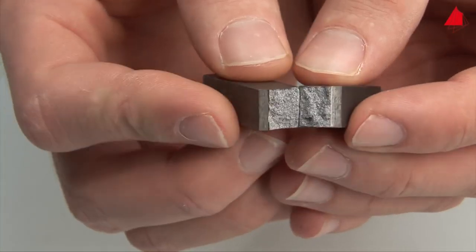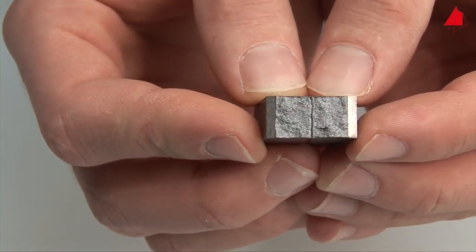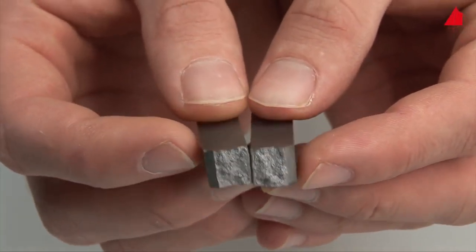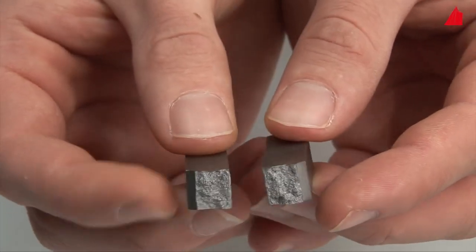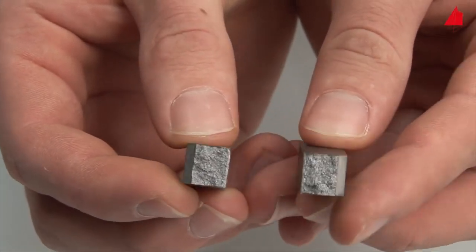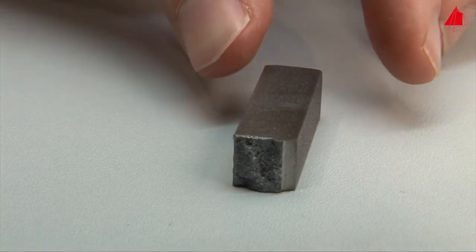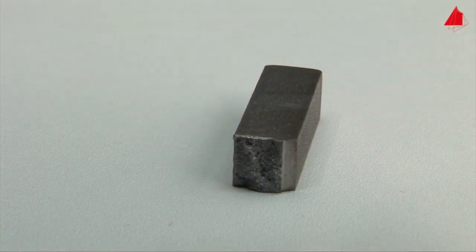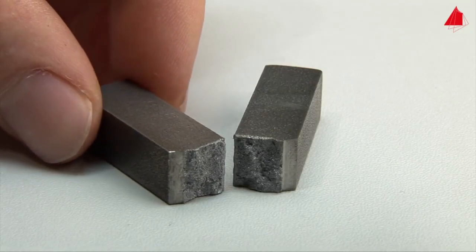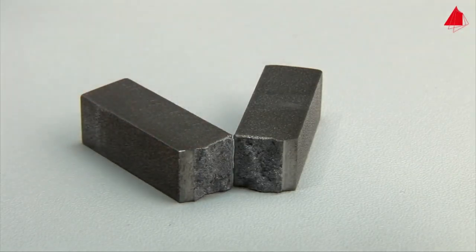The first specimen only shows very little plastic deformation. A mostly flat, slightly glittering fracture surface has been formed. This is another important indication that this kind of steel is only able to absorb small amounts of notch impact energy. It shows mainly brittle behavior due to the strain ageing effect.